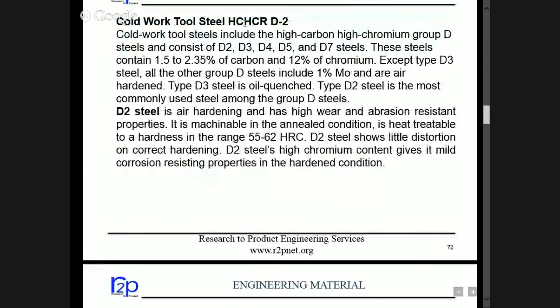Then is the cold work tool steel high carbon high chromium, D2. This is, you can say, in the cold work tool steel, the best steel is the D2 steel, very popular, where the volume is huge. Then we go for D2, which is expensive. So carbon is 1.5 to 2.35, and chromium goes up to 12%. So it's almost becoming stainless steel. D steels, except D3 steel, all the other group D steels have around 1% moly and are air hardened. D3 steel can be oil quenched. And type D2 steel is the most commonly used steel among the group D steels, very popular.